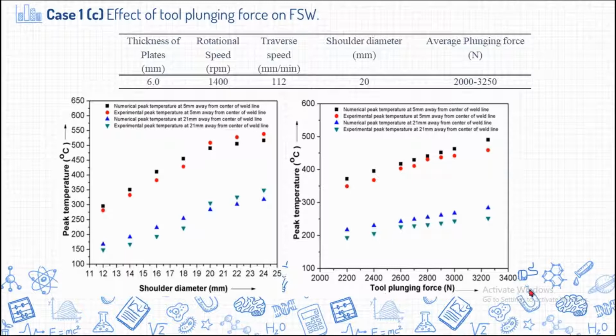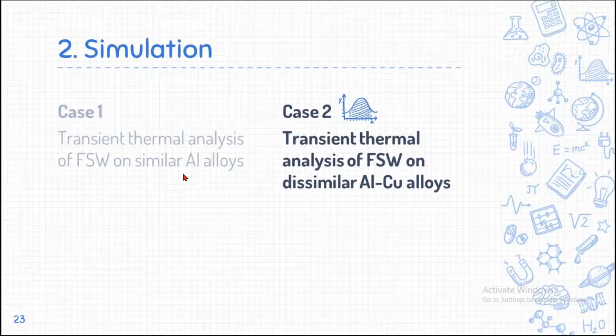So with various plunging forces, by increasing the plunging force, we obtain a peak temperature around 450 to 500 degrees. With more than 3000 Newton to 4000 Newton force, one can get around 75 to 85 percent of the melting point temperature of that particular plate to be welded.